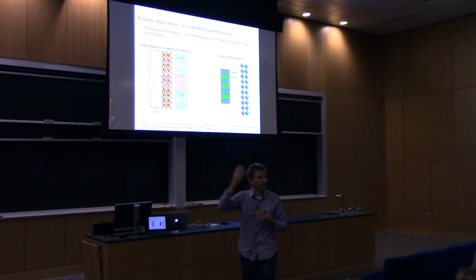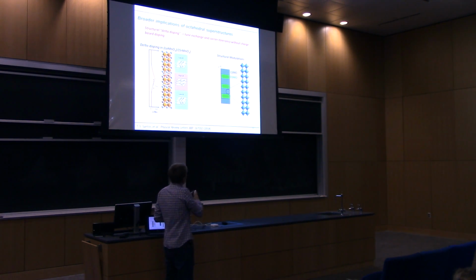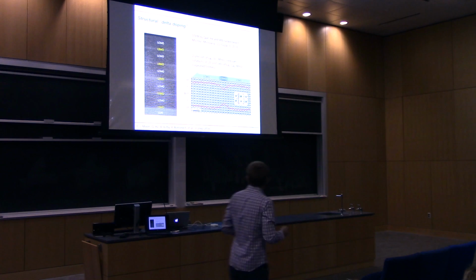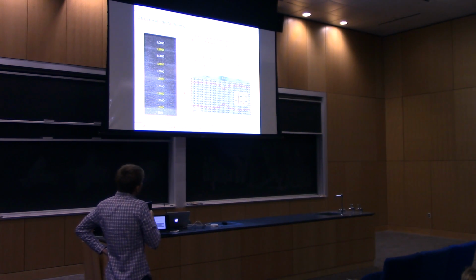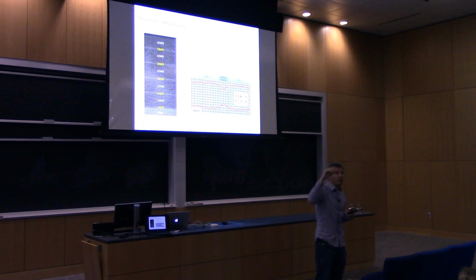No charge is getting transferred between the layers, but structure is getting transferred between the layers. These octahedral rotations are coming out of one layer and going into the other. So we can do a lot of the tricks that can be done with delta doping, but now do it structurally. Well, is that actually true? Can we push this to the limit of delta doping where we just put in a couple unit cells? So here's some recent unpublished work where we're looking at, again, isovalent manganite superlattices, 2 unit cells of this lanthanum strontium manganite inside 20 unit cells of lanthanum calcium manganite. Again, LSMO is going to have fewer rotations, so it should have larger electronic bandwidth and larger ferromagnetic exchange.